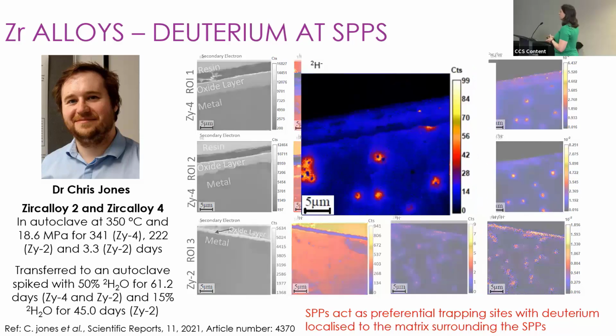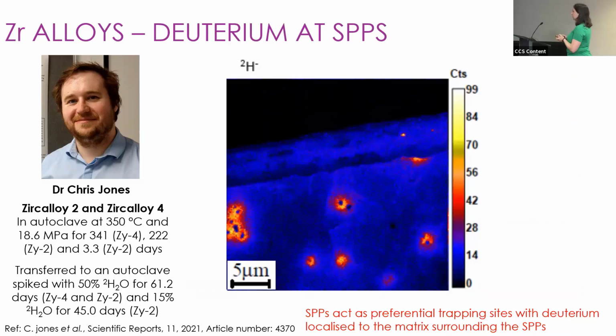So if we zoom in on one of those regions, it's very clear that they have a hole in the middle. And with some correlative imaging with SEM and EDX, we can identify that these are the secondary phase particles inside the zirconium alloy, so our iron, nickel and chromium-rich SPPs in these alloys. And so it's very clear to see that the deuterium appeared to be segregating around the edge of these, and with some complementary modeling, we could prove that this deuterium was localized to the matrix surrounding these SPPs, associated with the strain field.